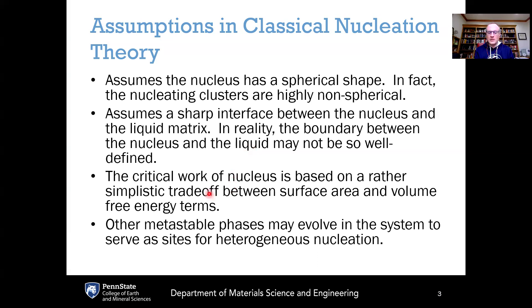Classical nucleation theory also assumes that the critical work of forming a nucleus is based on just a simple trade-off between the free energy penalty associated with interface formation and the benefit to free energy that comes from the volumetric free energy terms. That might be overly simplistic as well. And finally, classical nucleation theory doesn't consider any metastable phases that might evolve on the path towards nucleation.